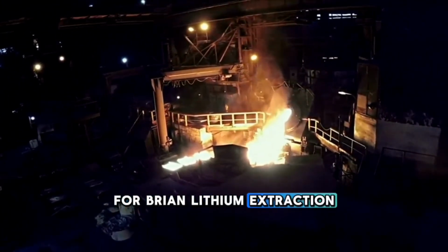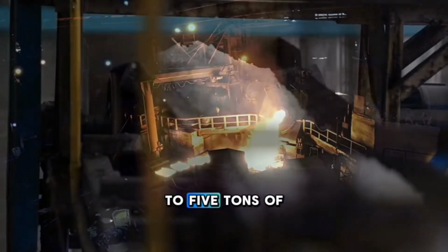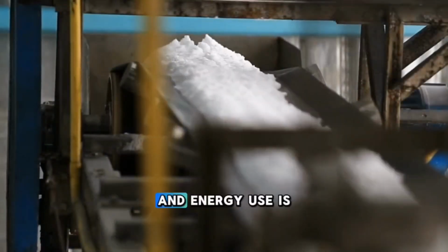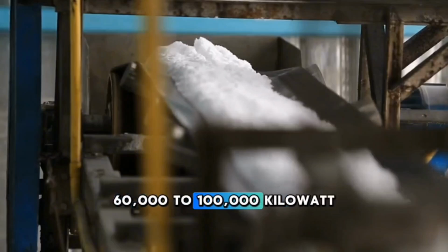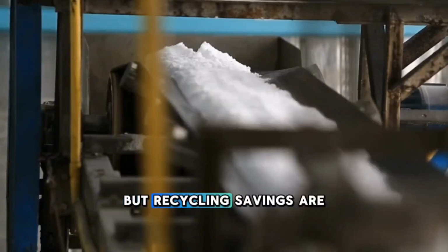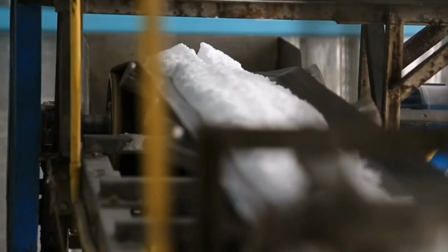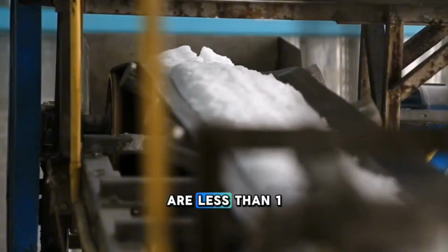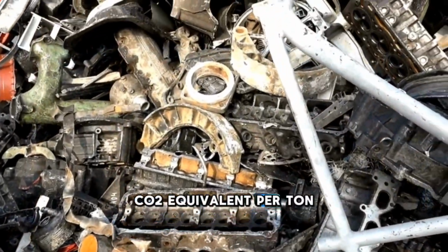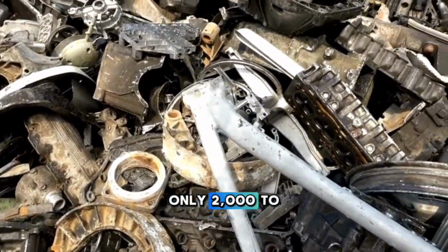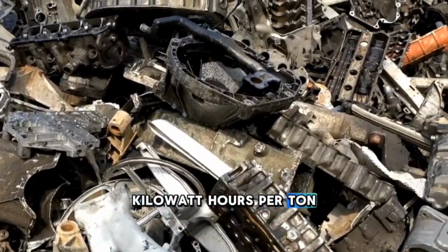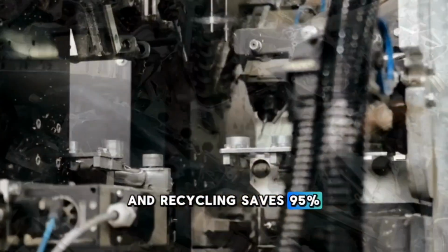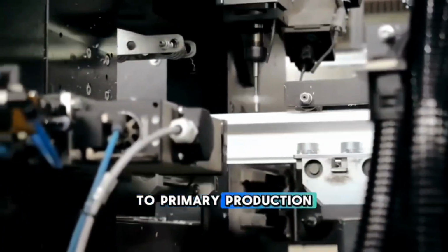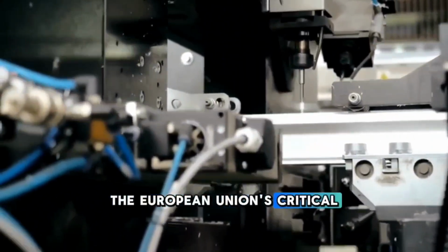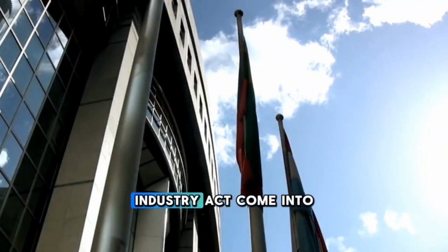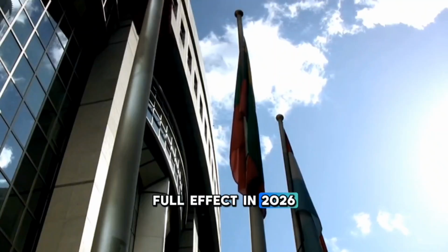For brine lithium extraction, emissions drop to 3 to 5 tons of CO2 equivalent per ton, and energy use is 60,000 to 100,000 kilowatt hours per ton, but recycling savings are negligible. For recycled aluminum, emissions are less than 1 ton of CO2 equivalent per ton, and energy consumption is only 2,000 to 10,000 kilowatt hours per ton, and recycling saves 95% of the energy compared to primary production. The European Union's Critical Raw Materials Act and Net Zero Industry Act come into full effect in 2026.